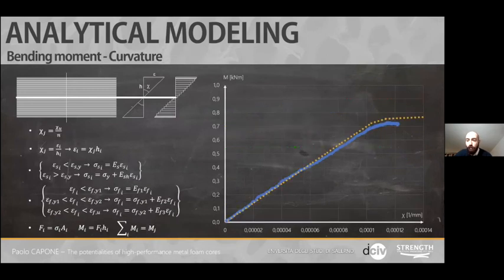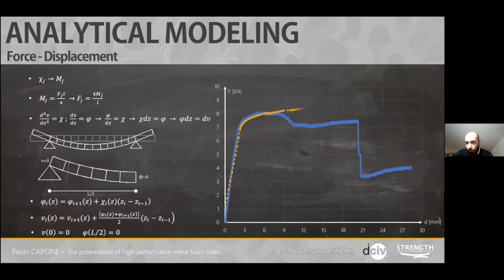Additionally, starting from the bending moment curvature relation, a step-by-step numerical procedure has been set up to model the force displacement curve. The main result of the analytical modeling has been that simple analytical equations can be easily applied to predict stiffness and bending strength of the panels. And we can see that step-by-step modeling also has a good match with the experimental results.